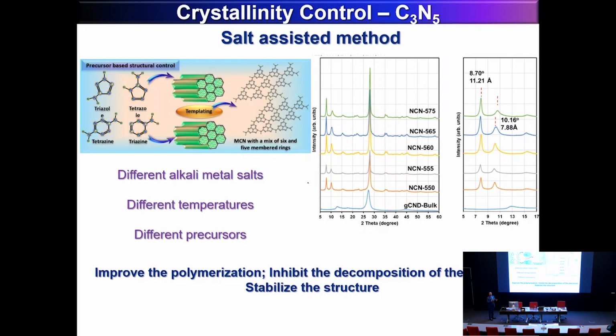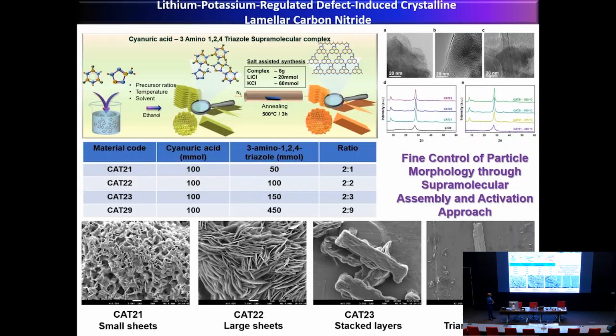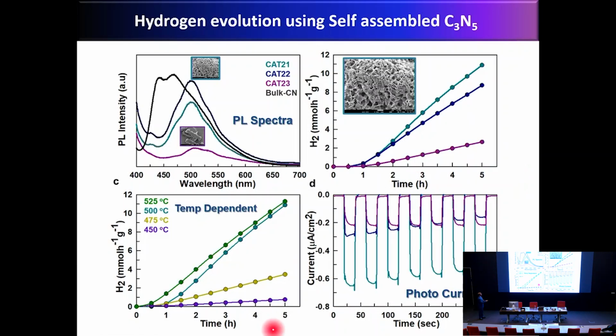With a crystalline carbon nitrogen wall structure, right? And we also integrated that one with a supramolecular assembly. In this case, we use cyanuric acid and triazole, with a different ratio. When we change that, together with the salt-assisted strategy, the morphology of the material changes from sheet shape to stacked layer to triangular prisms. And that makes a huge difference in the final performance of the material.